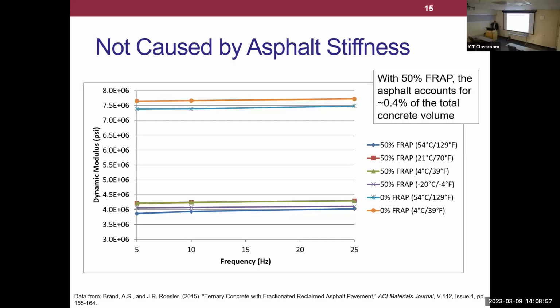So first off, the first thought people had was, okay, your modulus is decreasing when you use RAP. Well, of course it is. Asphalt binder itself has a much lower modulus than concrete. No surprise there. But we actually proved that wasn't the issue. We went and froze the concrete, to the point at which asphalt becomes stiff enough to be close to concrete, and we basically found that the modulus didn't change.